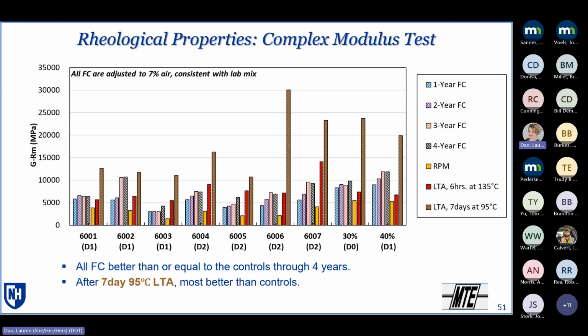You can see here, these are set up the same way as the previous, except here we do have the 3-year field core results. You can see that all the field cores have a lower Glover-Rowe mix parameter value, which again is better in terms of what we expect for cracking resistance. They're either better than or equal to the controls over 4 years. So it supports what we saw with the binder testing, that so far in place, they're still maintaining that benefit of the RA over the 4 years in place.